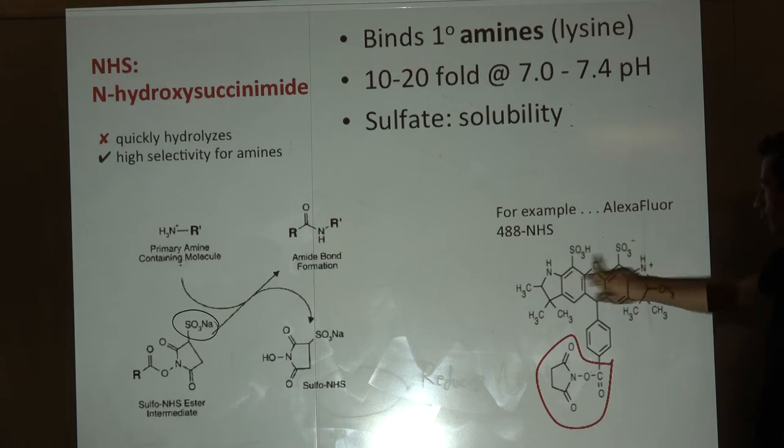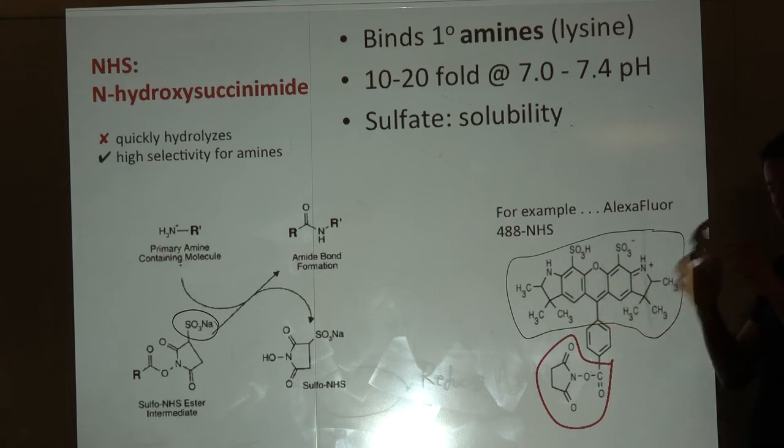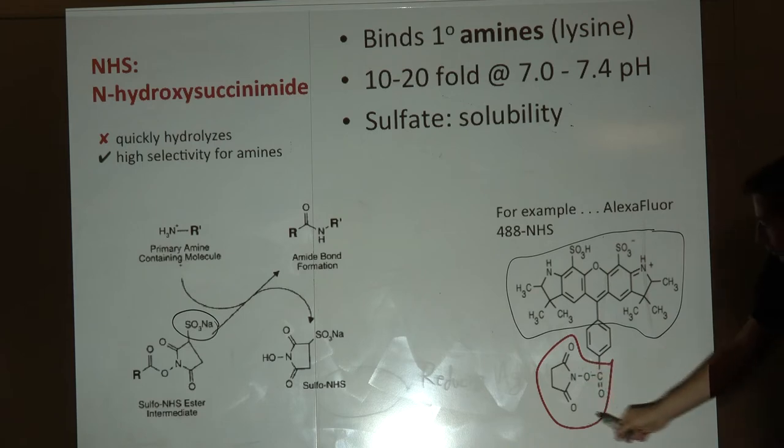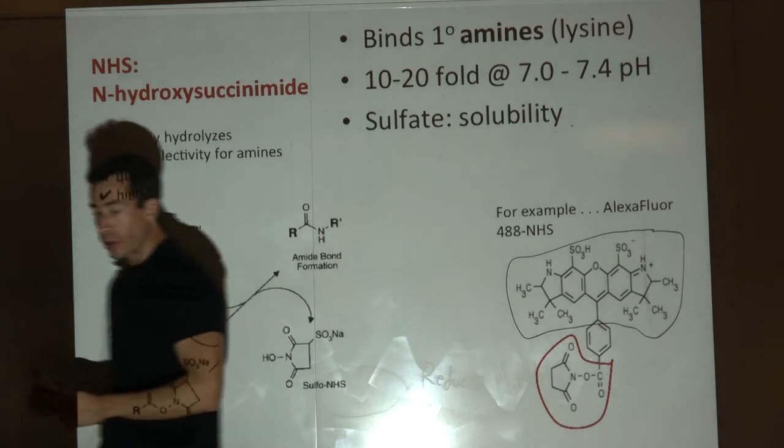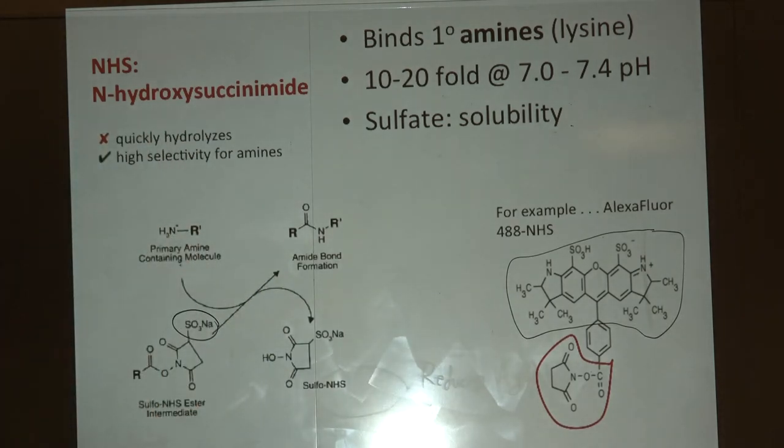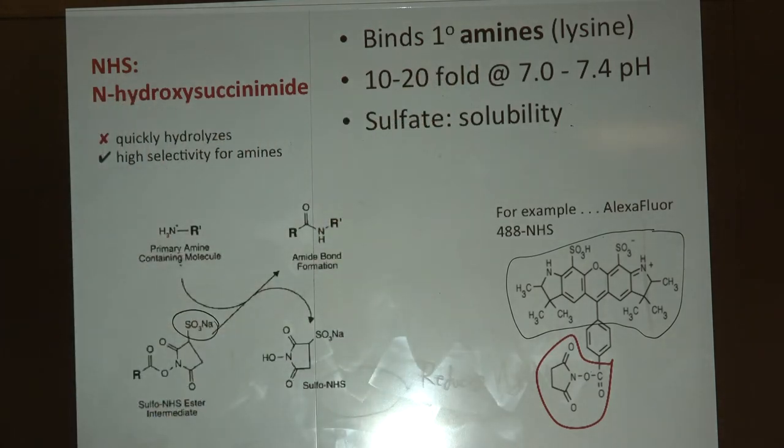One issue, it's very reactive with water. Water can hydrolyze it. Once you dissolve this into buffer and add it to your nanoparticle, use it right away. There are many commercially available reagents with this group. This is Alexa Fluor 488, where this part is fluorescent and here's our NHS ester.